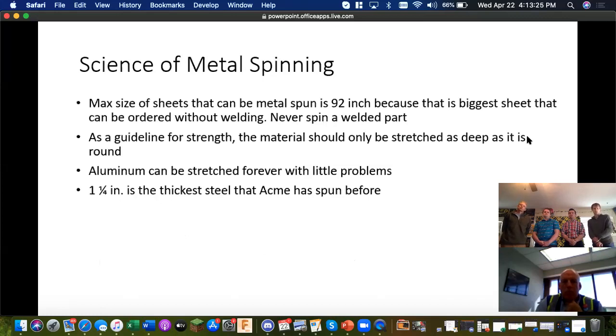into some dangerous situations. As a guideline for strength, the material should only be stretched as deep as it is round. If you put too much of a draw depth on the part, it can severely weaken the final product. Aluminum can be stretched basically as far as you want without problems, as long as it stays above a minimum thickness. And for steel, the thickest steel that ACME has ever spun is 1 1/4 inches, but they believe they can do up to 1.5 inches without a whole lot of problems.